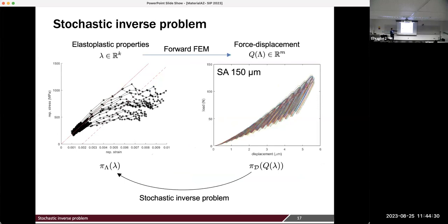Yes, absolutely. This is actually thousands of measurements, what you're saying right now. We are all looking at different measurements. It's all in the same sample. This is the real data that I'm showing you. Not a thousand different samples. This is one sample. You take multiple measurements as much as you can, and then we use that variability to figure out the variability in the elastoplastic properties.